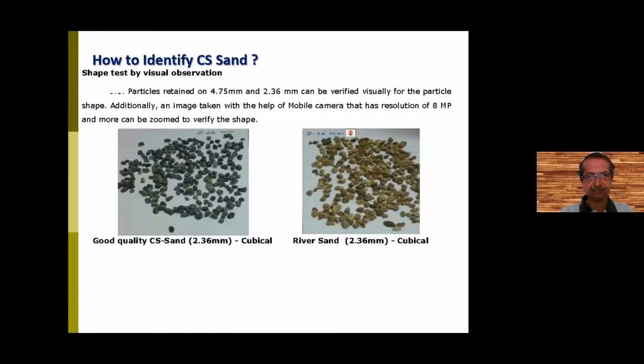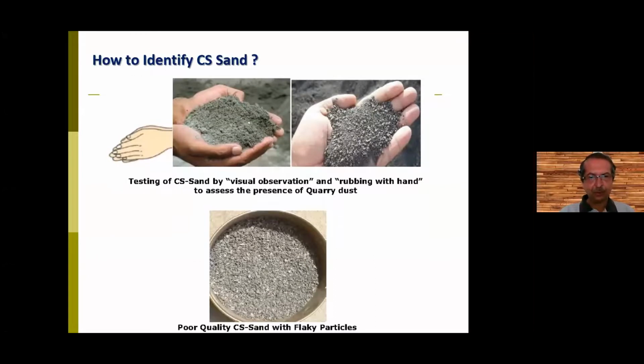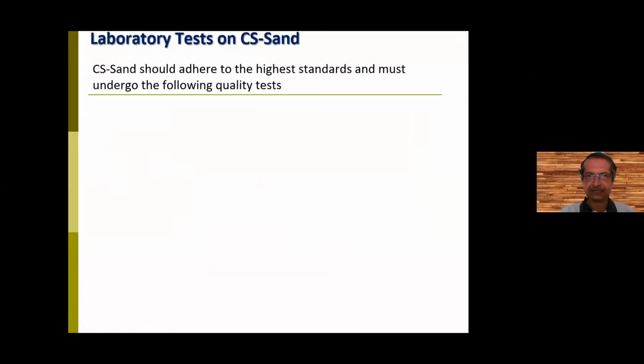For your information, for your benefit, the photograph is shown. On the right side is river sand, left side is good quality crushed stone sand. Both of them are of 2.36 millimeters, so they will appear identical. But if there is quarry dust mixed in it, very easily you can make out when you zoom the photograph taken from your smartphone. Very simple. So the poor quality crushed stone sand will have flaky particles, something that you must remember to identify or distinguish. So crushed stone sand, strictly speaking, should have compliance to several standards, but you may not do it